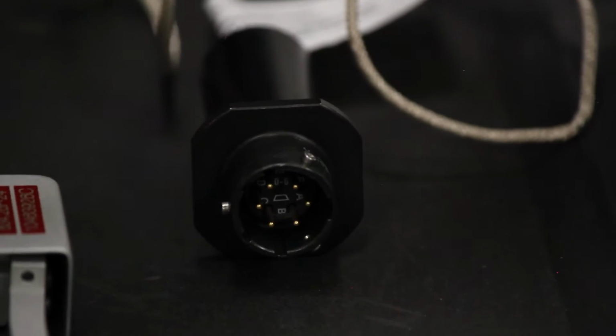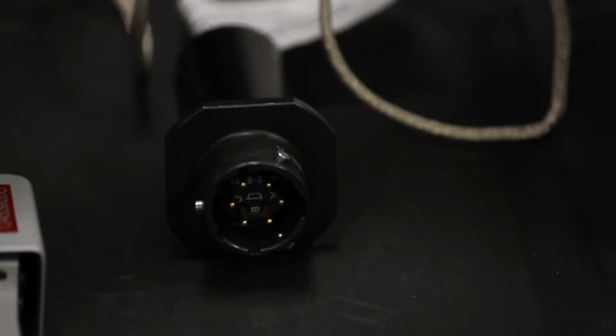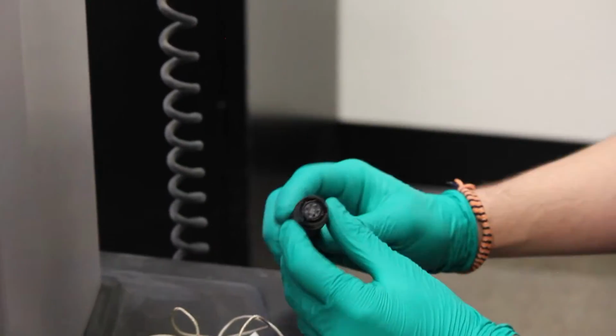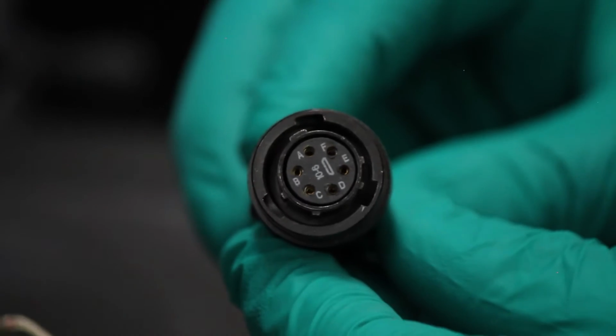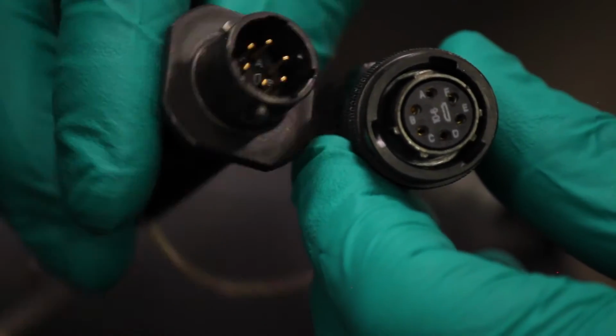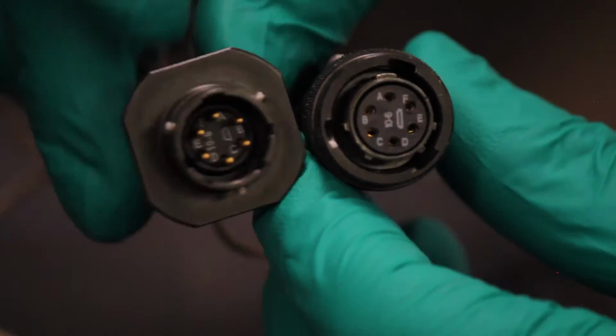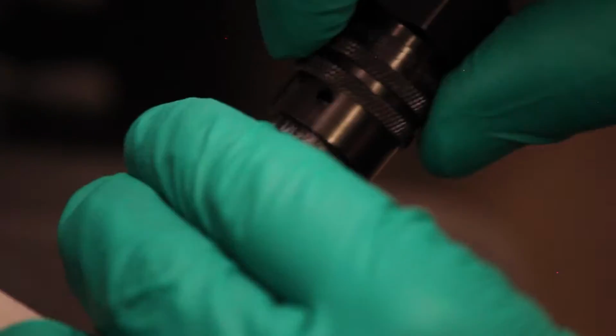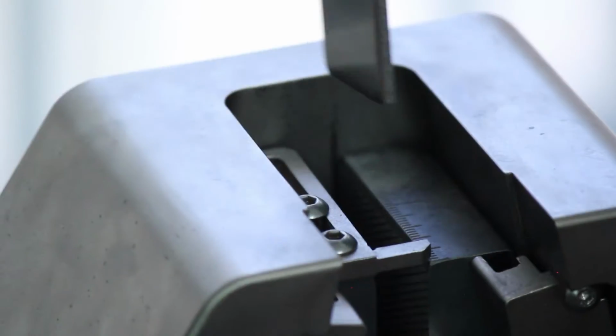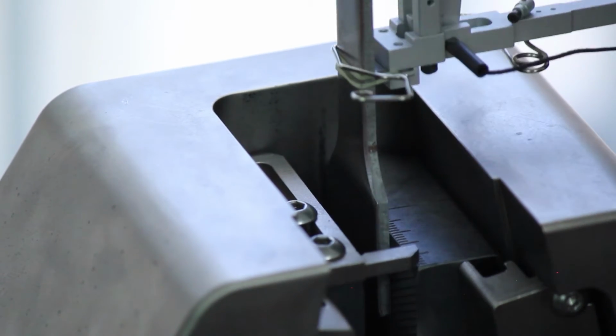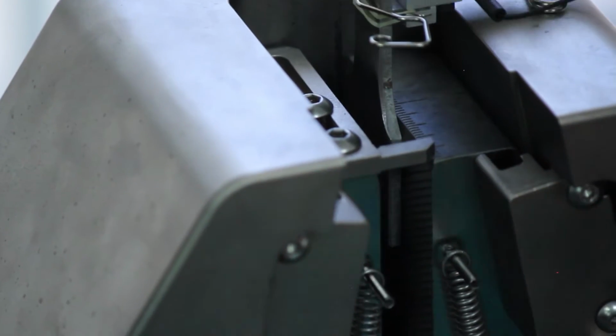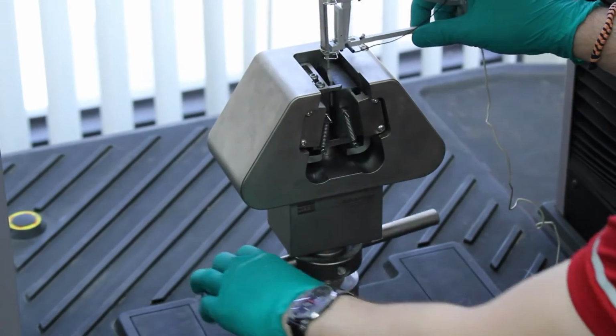Before plugging the extensometer into the tensile tester, make note of the letters located next to each pin on the plug. The plug coming from the tensile tester has letters corresponding to those pins on the extensometer. When connecting the two, there's a ring located around the edge of the one coming out of the tensile tester, which you must twist and will click and lock into place. Now, when you're mounting your tensile sample into the tensile tester, be sure that the shoulder of the tensile sample rests below the top of the grips.